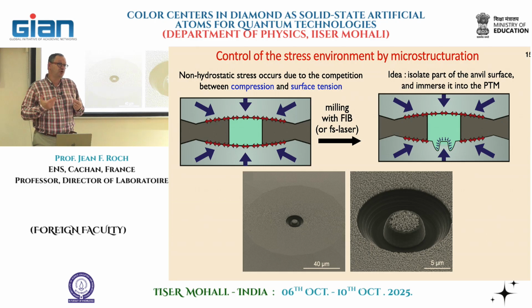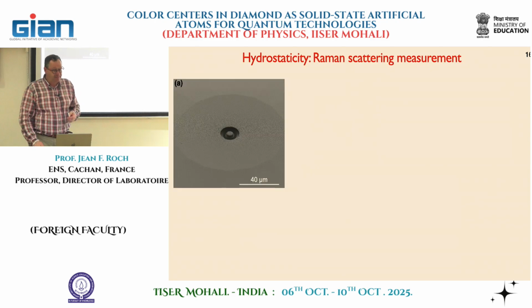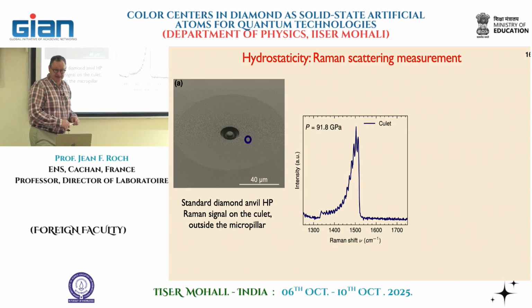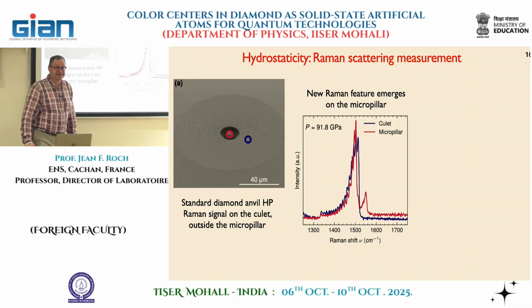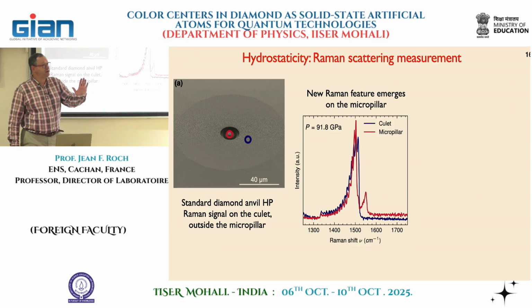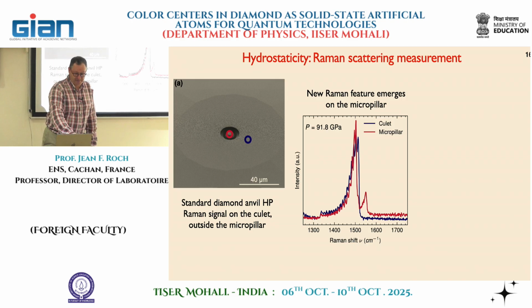And the first check is to look at the Raman signal of the diamond. The Raman signal is already a good signature to get an insight of the stress environment. So if we look outside the sample, we have this typical signal, and that typical signal can be explained by non-hydrostatic conditions. If we now look exactly on the pillar, we see a new peak that arises, and this new peak with a higher Raman shift is actually evidence that there is a higher pressure exerted here compared to here, on the red dot compared to the blue dot.